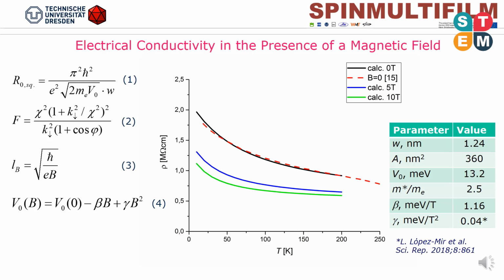In the low voltage regime, supposing direct tunneling through thin enough barriers, the sheet resistance of a granular nano-sized strontium ferromolybdate strontium molybdate core shell structure, up to a factor of F, is given by equation 1, where e is an electron charge. The factor F depends on the ratio of the reciprocal localization length and the wave vector of the wave function of the tunneling spin down electrons, as well as on the angle phi between the magnetic moments of the neighboring grains.